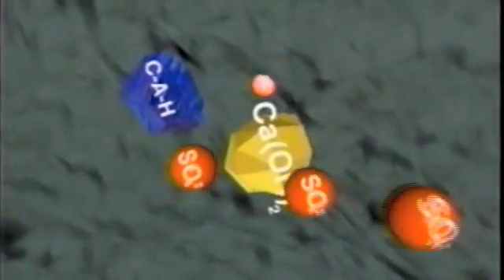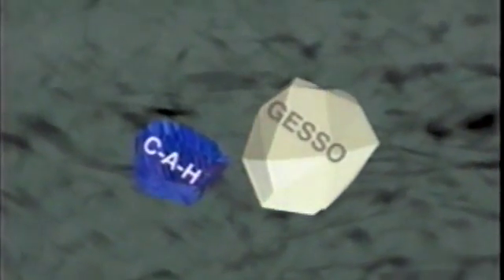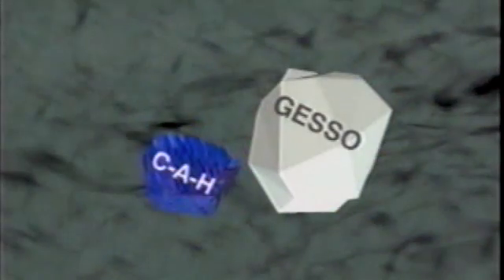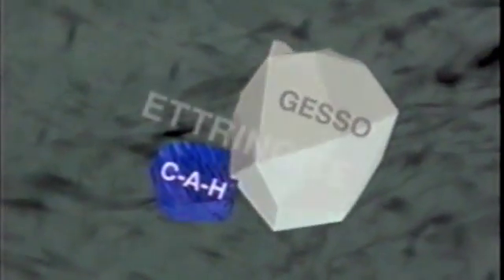Sulfate reacts chemically with the calcium hydroxide present in the concrete mass and transforms it into the more voluminous gypsum. This product reacts in its turn with the hydrous calcium aluminates, here shown as C-A-H, transforming it into ettringite. This transformation also results in an increase in volume in the material with a disastrous effect on the structure.